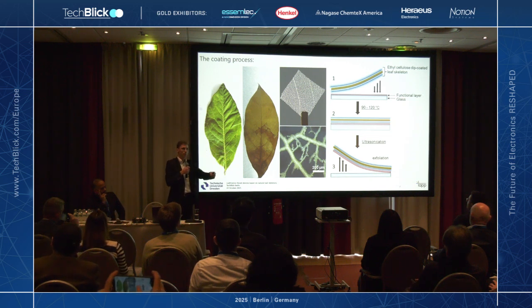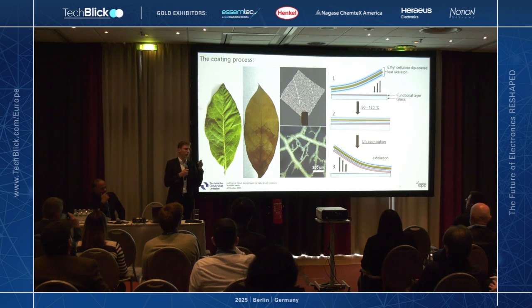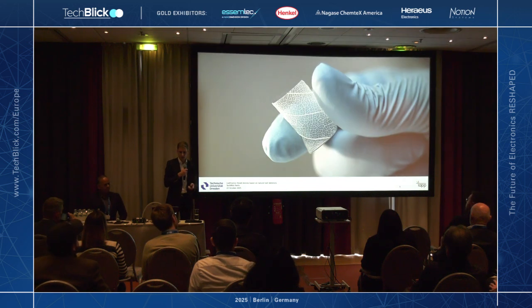By using this structure and putting a chitosan layer on top, exfoliating from a glass substrate, you get an ultra smooth surface with a chitosan layer where you can print on top. The surface energy is very well suited for printing, and the smoothness is perfect even for evaporation of nanometer thin semiconductor layers.